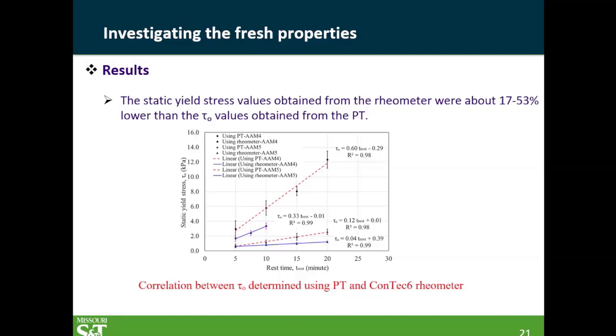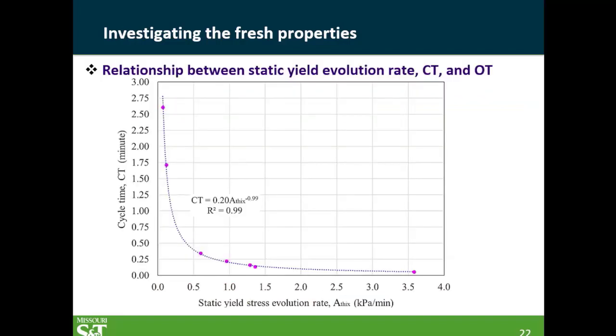So there is really a very strong correlation between the penetrometer and the static yield stress, given the fact that the penetrometer is much easier to do and can be used for quality control rather than the viscometer. And then what's really important in the end, we have a correlation between the cycle time and the static yield stress, and we correlate them through this one. So if you know your cycle time, you can figure out how much static yield stress is required, or vice versa.